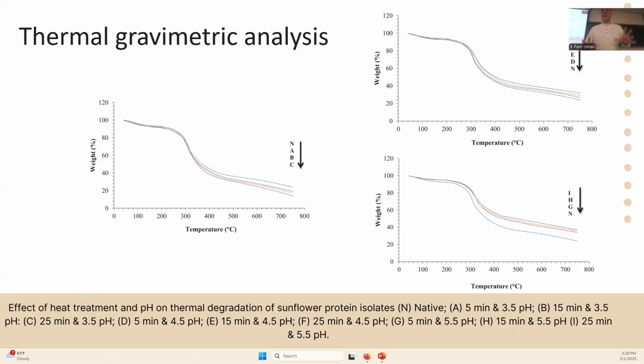From the figure we can indicate that at pH 4.5, there is more aggregation of protein molecules as compared to pH 3.5 and 5.5, thus allowing higher thermal stability. Increasing heating time at each pH value further increases the thermal stability, suggesting lower weight loss in preheated protein isolates in response to the temperature.